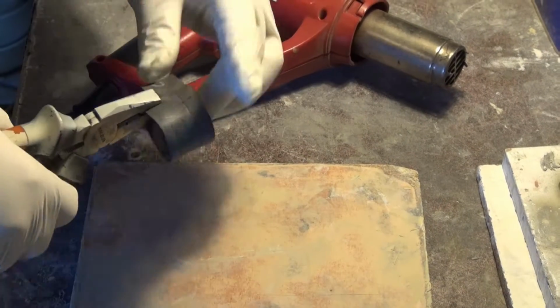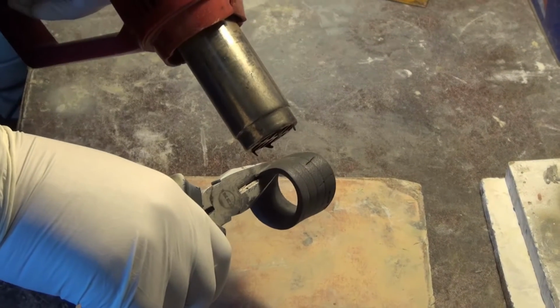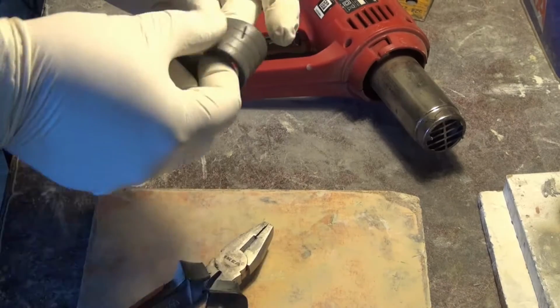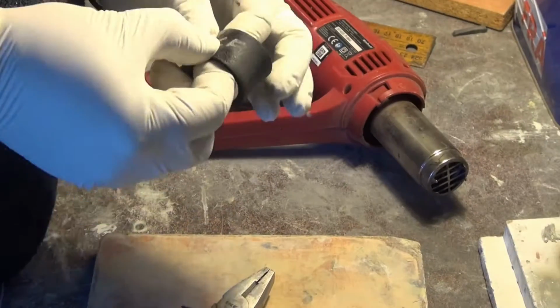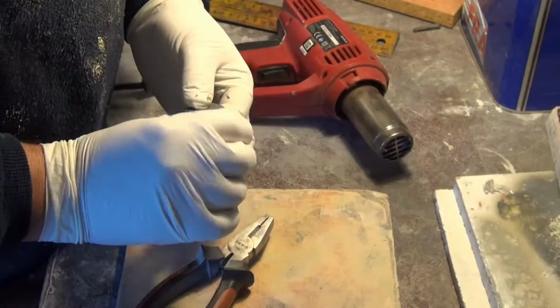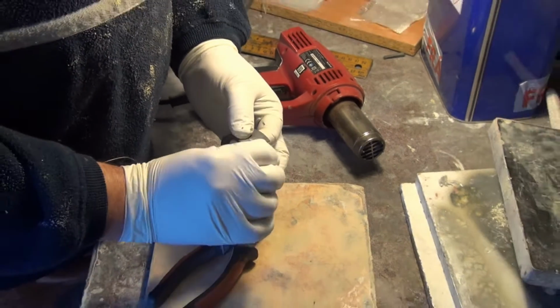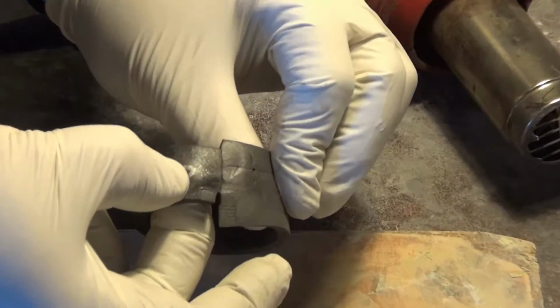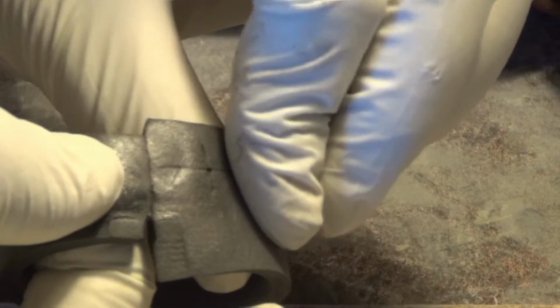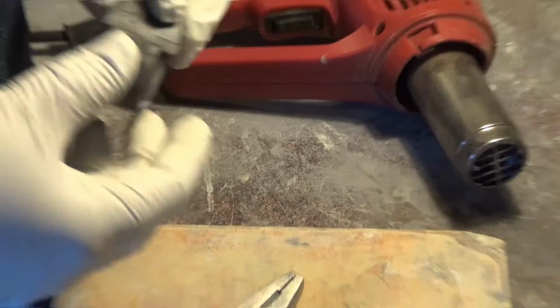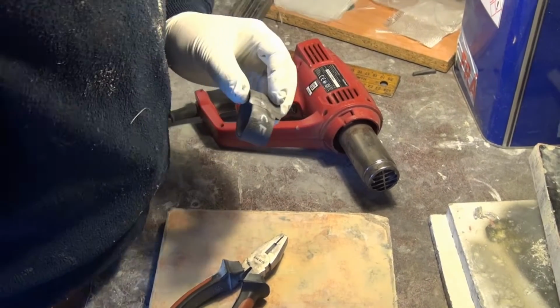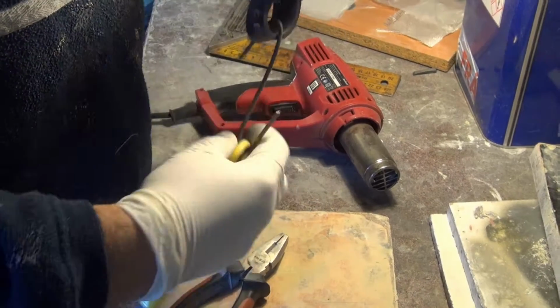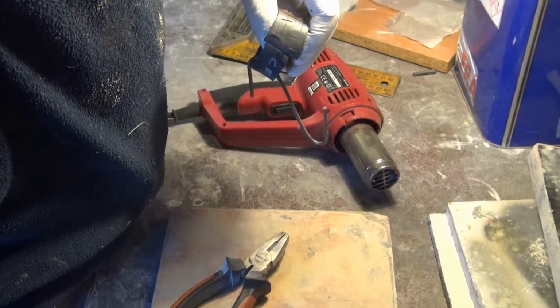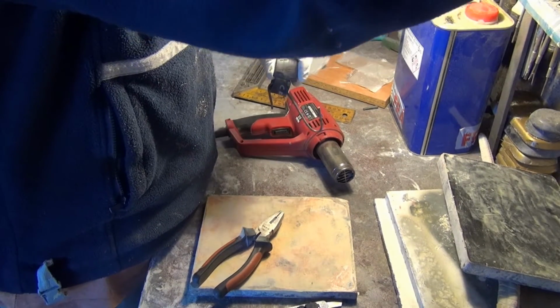The first sample to be tested was craftfoam. Heating both ends of a strip of foam, it was possible to create a ring. In order to test the resistance of the bonding, we used a wrench with an approximate weight of 400 grams and hung it from the ring.